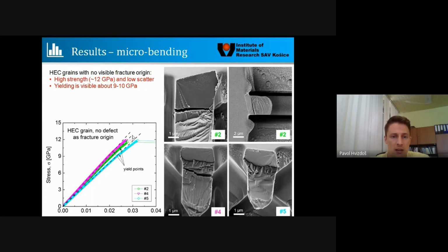Here we can see that the strengths were quite similar. They were basically 12 GPa, which is quite high. We hardly see any fracture origin, and what we see is a slight yielding at about 9 GPa, but they are basically linear, with only a slight plasticity or slight deviation from linearity before the final failure occurs.